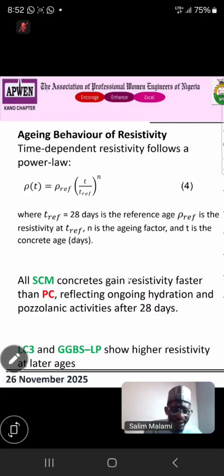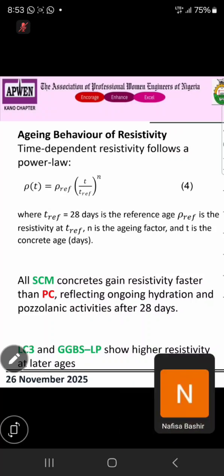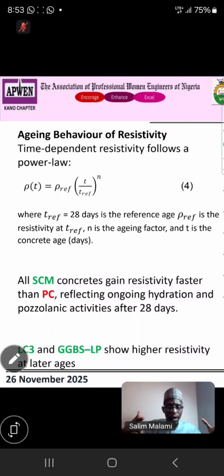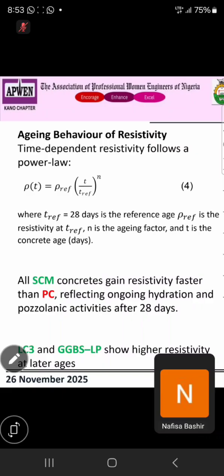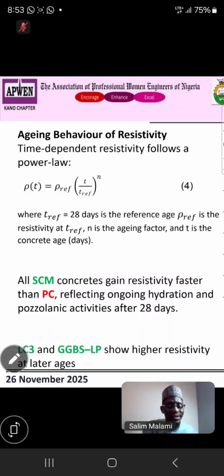So all SCM concrete gain resistivity faster than PC, as I have already mentioned, reflecting ongoing hydration, which I have already explained. And pozzolanic activities are reactions that happen due to some chemicals or calcium oxide inside the concrete. They also increase the strength of the concrete. So because of that hydration and pozzolanic activity, the low carbon concrete has higher resistivity. So LC3 and GGBS show higher resistivity at later age.